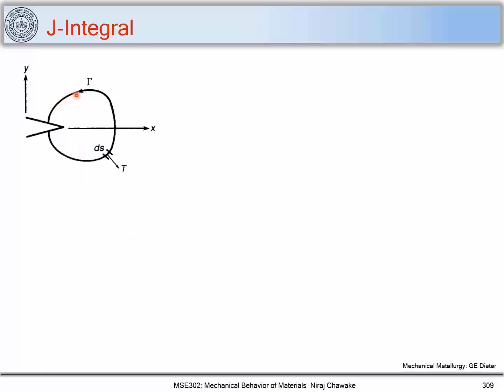Now we have to find out the non-linear strain energy release. So let's consider this crack, and let's consider this as the X direction and this as the Y direction. These are our coordinates, and let's consider this line which is given by capital gamma. To find the J integral, that is the non-linear strain energy release rate, we do it by finding a path independent line integral. So we consider this to be the path. Let me mark it over here. We mark a path in this way, and we enclose this crack with this line, and that is why I mentioned that this is a line integral to find J, which is nothing but the non-linear strain energy release rate. Let me write that down also. So J is nothing but the non-linear strain energy release rate.